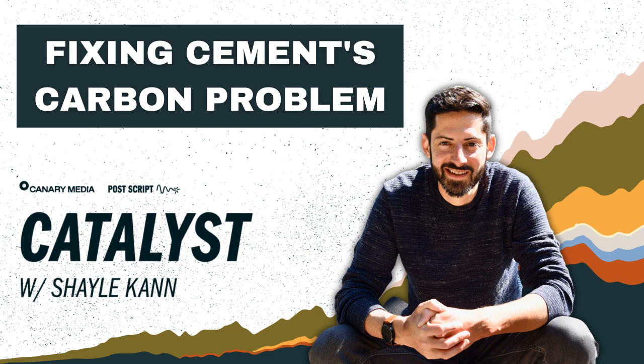And this is what makes cement one of the most difficult things to decarbonize from a technical standpoint, is that you need limestone, so you need the calcium oxide, and then you also need to get to these high temperatures to make the calcium and to make the silicate. So there's almost no way around that except for post-combustion carbon capture if you're making Portland cement.